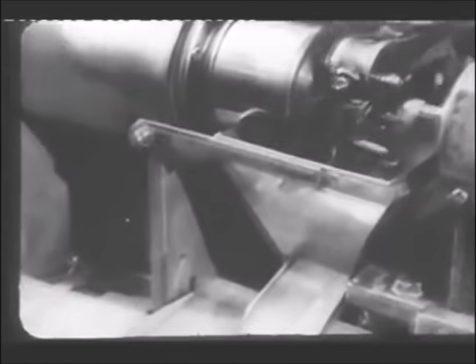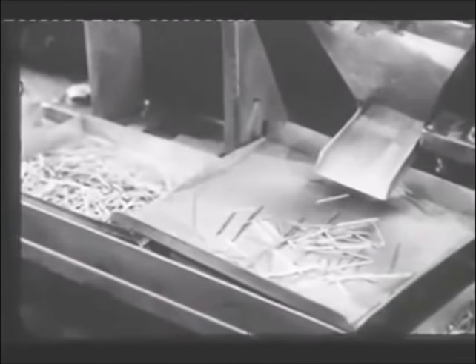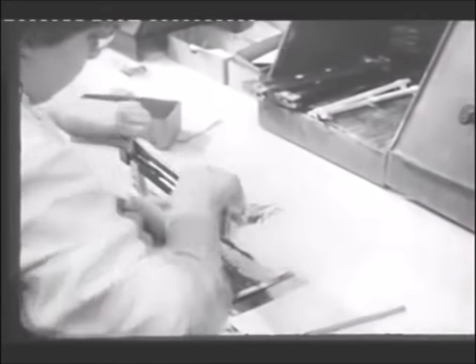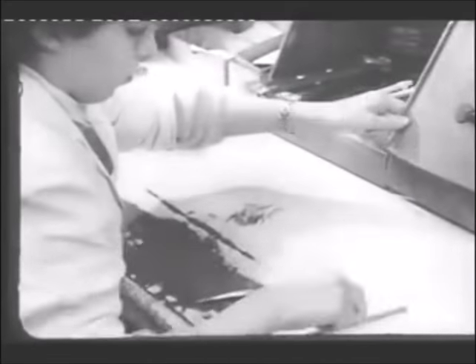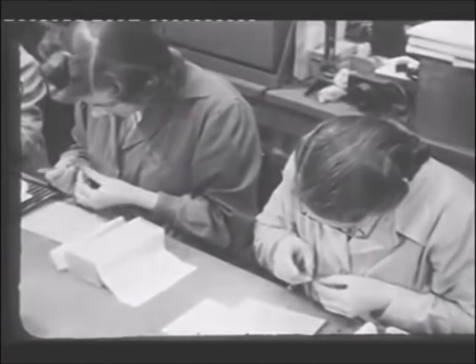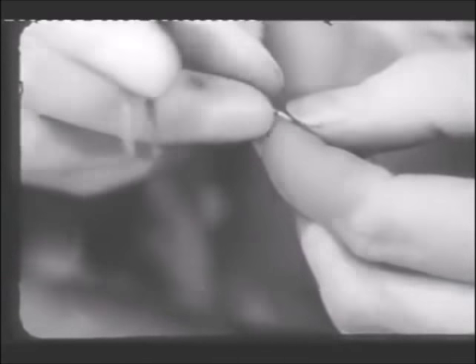Nickel cathode tubes are cut to length, mounted in frames, and sprayed with barium and strontium carbonates, from which the emissive surface is produced later on. In this case, the heaters are inserted into the coated tube at an early stage.